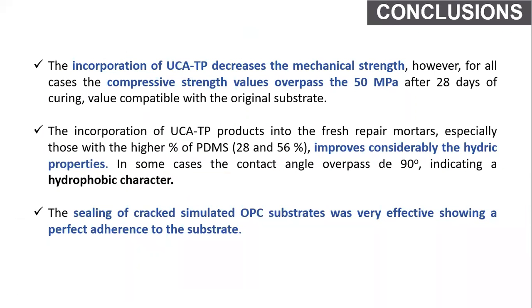So finally, to conclude, I would like to point out that the incorporation of the UCA-TP products decreased the mechanical strength. However, in all the cases, the compressive strength overpassed the 50 megapascals, a value compatible with the original substrate. The incorporation of the UCA-TP products into the fresh repair micromortars, especially those in the highest dosification of polydimethylsiloxane, improved considerably the hydric properties. And finally, the sealing of cracks in simulated OPC substrates was very effective, showing a perfect adherence to the substrate.